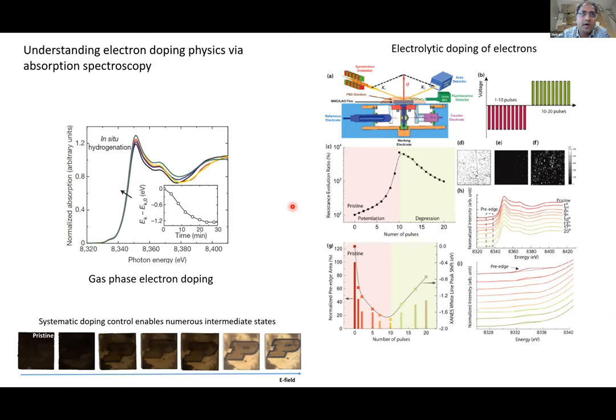For hydrogen, we have found there are many more approaches. But at the same time, if we can introduce ions like lithium through solid state reservoirs, you may be able to accomplish the same thing. The only other thing we noticed was that the dynamics was much slower. We can do proton at fast, high speeds, whereas some of these other ions, especially if you're introducing them from liquids, are much slower.